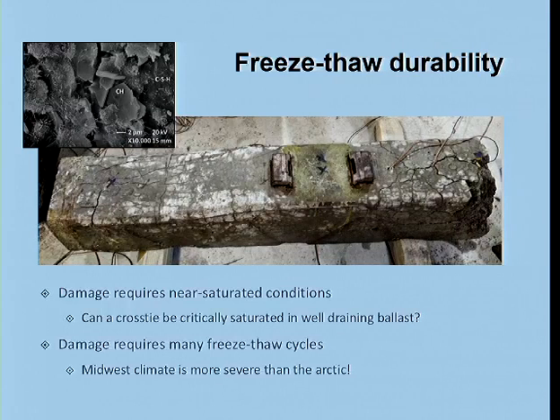And so we then realize that damage under freeze-thaw conditions requires something near saturated conditions. If the concrete was completely dry, there would never be any motivation for this concern. But we have this porous microstructure that can draw water in from its environment. So one of our questions early on was, can a concrete cross-tie be critically saturated in well-draining ballast?